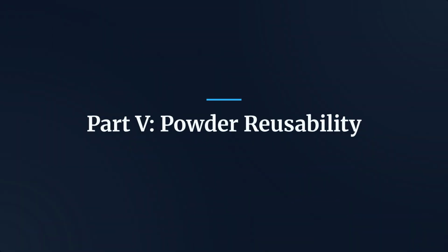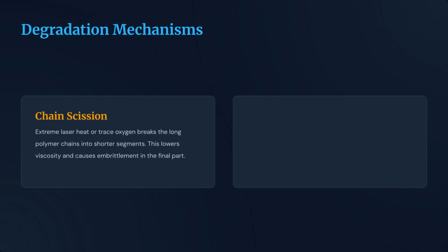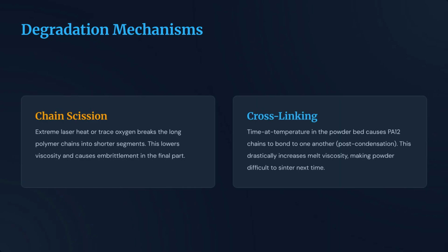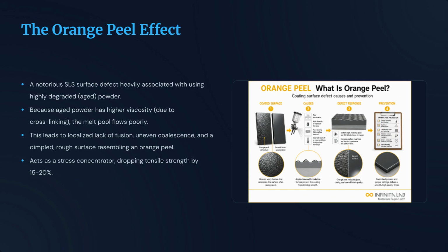This brings us to Part 5, where we discuss powder reusability and the mechanisms that cause degradation over time during the build process. Degradation generally occurs through 2 mechanisms: chain scission, where heat breaks polymer chains, causing embrittlement, and cross-linking, where chains bond together, significantly increasing melt viscosity and hindering future sintering. The orange peel effect is a common defect caused by using highly aged powder. Because the viscosity has increased, the melt pool fails to flow correctly, creating a rough surface and reducing the tensile strength of the finished part.